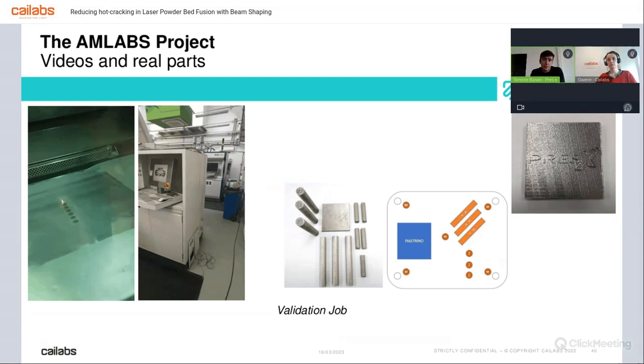This is, as I told you before, the validation job. And unfortunately, we were not able to print a fully complete part, basically because it requires several days, and this was a short project. So if we have some troubles with the printing, then we need to start again, and we will probably run out of time. So this was just a part, but the idea is that we have printed a part that is completely crack free, that is completely fully dense. It's in Inconel 939 with an old machine. It's a really nice result.